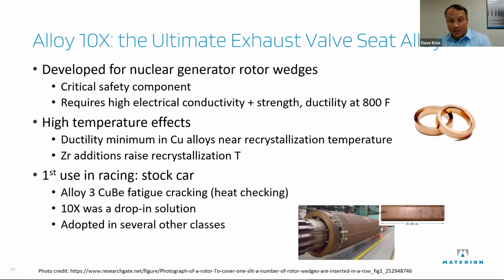And rotor wedges go in these slots that you see on this big Siemens rotor wedge. And this thing is, I think it's like 6 feet in diameter and 30 feet long, and it spins at 3,000 RPM. And the rotor wedges keep the windings from flying out, which can cause all kinds of bad things to happen and pieces of metal to fly everywhere. So the rotor wedges have to be durable. And there's a condition, at least at one point in the design of these, where there might be enough current through the rotor wedge to hit 800 degrees Fahrenheit. So it had to hold the strength at 800 Fahrenheit, right?